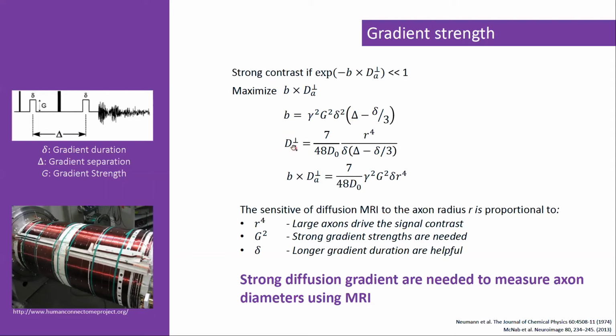The intraaxonal diffusivity perpendicular to the axon is actually a feature that has been studied in depth as a function of diffusion times in various regimes. But in the regime that's most relevant to us, Neuman did quite some work in the 70s already, showing that the diffusivity relates to the radius to the power of 4 and diffusion time. So if you make the product of those two variables, we actually get a rather simple equation that shows that if we want to be sensitive to axon diameters, we have to maximize this number. And that means that we need large axons, because large axons, R to the fourth, drive the signal contrast.